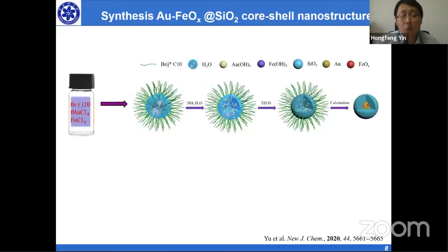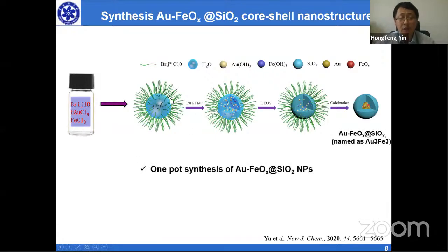This is one-pot synthesis of gold iron oxide in silica. The silica is a shell. For example, we use the surfactant, the gold precursor and the iron precursor. By reverse micelle reaction, it will form this gold iron oxide with a silica shell nanoreactor.